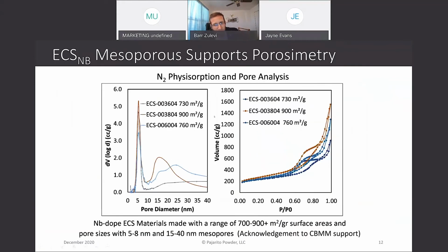If we look at nitrogen adsorption, which we use to estimate and quantify the structure of the support, we can see here on the left a mix of pore sizes and pore volumes around the 5 to 8 nanometers that we can control, as well as surface areas ranging from 700 to over 900 square meters per gram, as well as our ability to change these larger pore diameters. This, of course, is analysis that comes from the right side of the nitrogen isotherms.